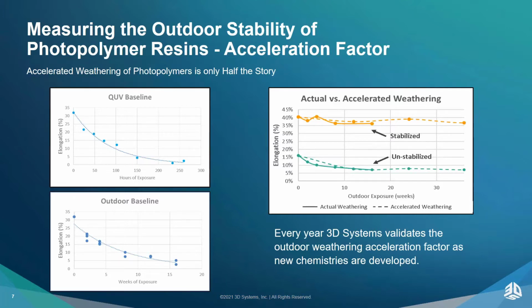After we thoroughly characterized one of our materials and developed a case study, we were able to generate these really lovely curves that projected hours of exposure, plotted as a function of decay of mechanical properties, which is really great. But without any baseline or relevance to show, it's very hard for customers to understand what 200 hours in a QUV replicates.